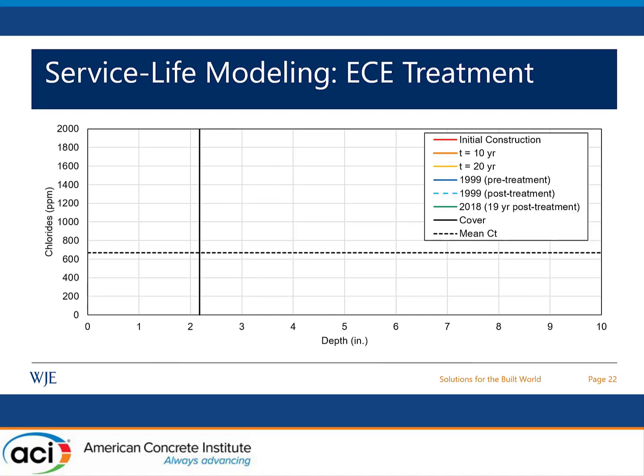We also performed a service life model looking at these two exposure classes, the high exposure and the low exposure. But our models also considered the effect of the ECE treatment itself. So I'm going to show an example of what the chloride profile might look like in one of these higher exposure areas. Initially we have no chlorides present, but over time, 10, 20 years, and all the way up through 1999, these chlorides are starting to build and diffuse through the concrete.